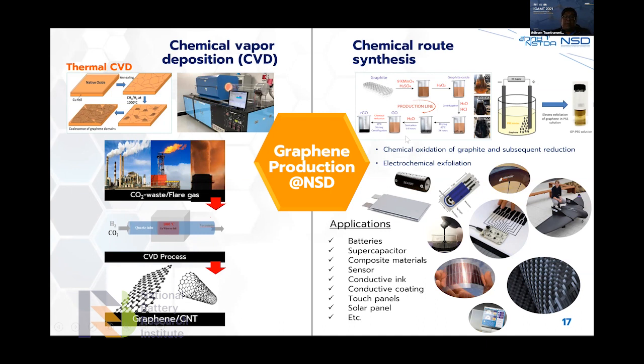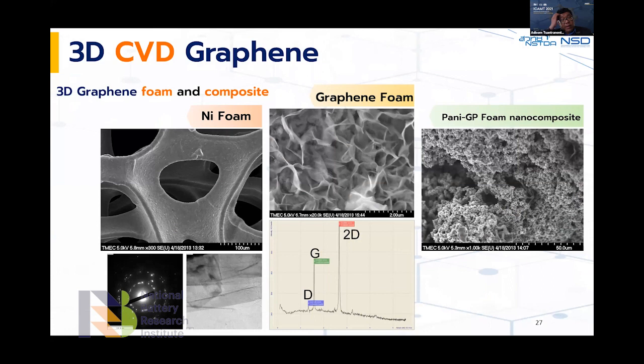And another technique we call chemical route synthesis. We focus mainly on electrochemical exfoliation because we have been filing patents on how to make graphene from graphite using an electrolytic exfoliation technique. And with both graphene productions at our center, we can apply them into many applications, including batteries. For example, in our research work, we use nickel foam as a template, and then we CVD graphene on top of the nickel, and then we etch away the nickel and composite the graphene with conductive polymer to make a nanocomposite.